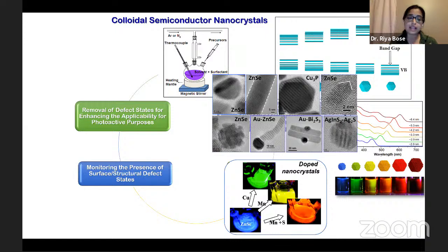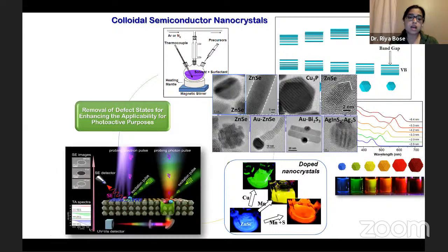And then we have also monitored the presence of surface and structural defect states. As I have said, these materials have a valence band and conduction band, and usually the emission we get is in between these two. But sometimes, because of structural defects, there are states incorporated in between the valence band and conduction band, which can capture the electron or the hole and hamper the recombination process, so we do not get the light we are aiming for. So we use either a light beam or electron beam to monitor the presence of these trap states.